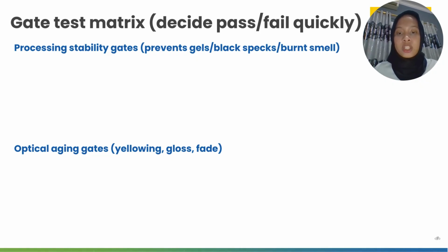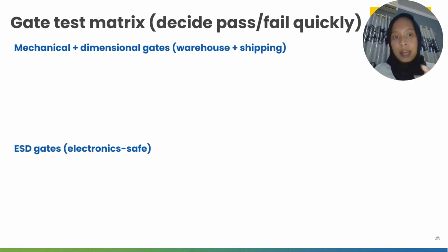For optical aging gates, which is yellowing and gloss fade, the test is UV-rich exposure on film and printed tray, and the condition is UVA or store light simulation plus oxygen, and the pass criteria is low delta b or yellowing, gloss retention, and acceptable haze. And the second one is hot or humid aging at 40 to 45 degrees at high RH, and the passing criteria is no over haze, no major brightness loss, no cracking or warping, and that is the suggested condition and pass criteria.